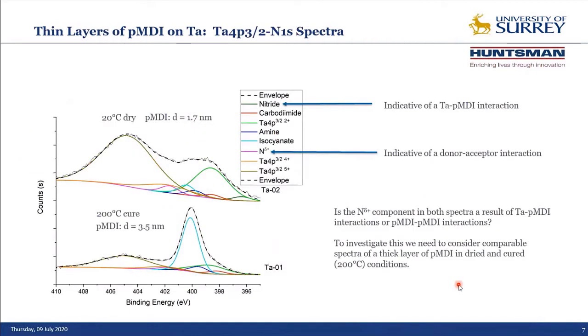So how do we deal with this in actuality? We're now thinking about our 2 tantalum specimens, both with a very thin layer of PMDI on them. One has been dried at 20 degrees, one has been cured at 200 degrees C. And as we saw from the XPS survey spectra, the thing that dominates the cured one is this component here, which is the isocyanate peak. We can see a couple of contributions there from the very weak tantalum peak. So essentially, our 3.5 nanometers of PMDI is all but obliterating the characteristic tantalum 4p3/2 spectrum.